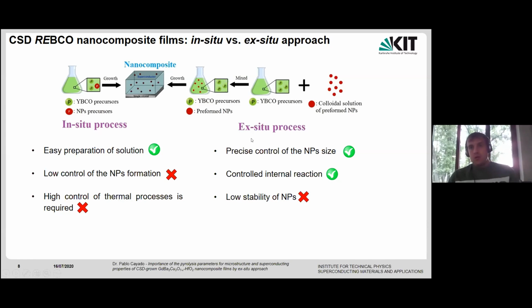In the other case, we have the novel ex situ approach, which is the main topic of this talk. It is quite a recent, quite novel technique. In this case, we first create a colloidal solution of preformed nanoparticles with a specific size and shape, and then we mix it with the YBCO or REBCO solution. Finally, we have a colloidal solution of the YBCO REBCO solution plus the preformed nanoparticles.